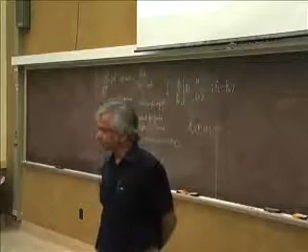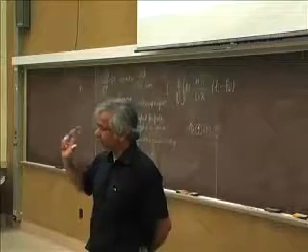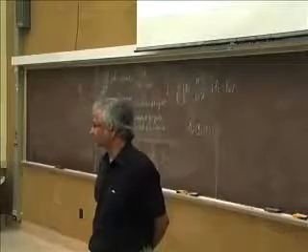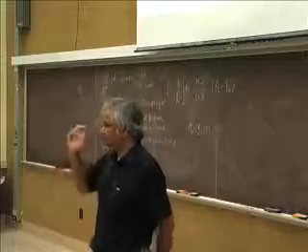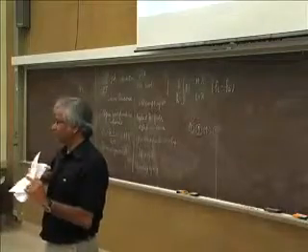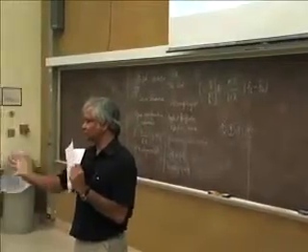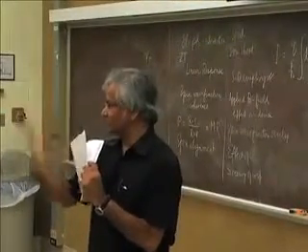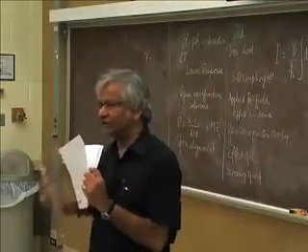Correct. Yeah. Thickness 20 nanometers sounds high to me for switching with spin torque. My guess is it would have to be more like 2 nanometers, from what I've seen. The thickness, yes. Area is fine, because it doesn't matter if it's big, since you're hitting the whole thing with spins. Right? So the point is, for every little unit cell you have a spin coming in. That's fine. So if the area is big, it doesn't matter.